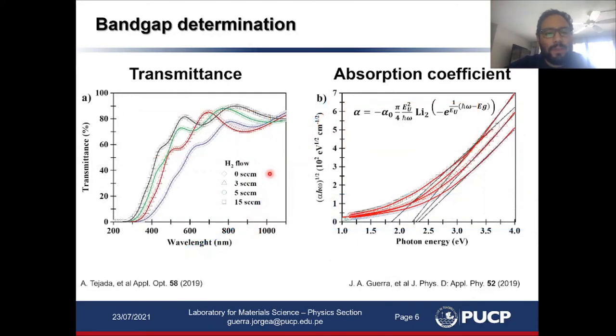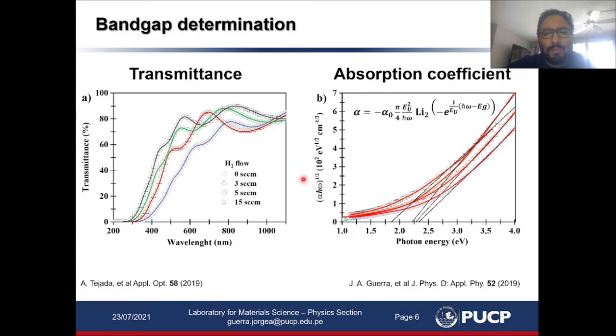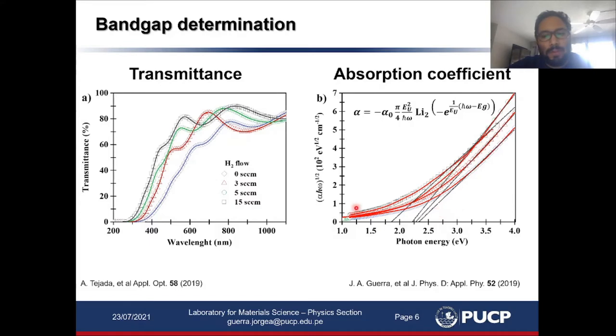We have grown samples with four different hydrogen dilution conditions during the deposition process: one without hydrogen and three with increasing hydrogen contents. From optical transmittance measurements, we determined the thickness, refractive index, and absorption coefficient by a method developed in our group, in a way that we do not use a dispersion relation to model the absorption coefficient. Here on the right, I'm showing the absorption coefficient of these samples in their as-grown state in the Tauc scale. Red lines correspond to fits using the band fluctuations model, while the black dotted lines correspond to fits using the traditional Tauc model, which does not take into account the presence of Urbach tails.